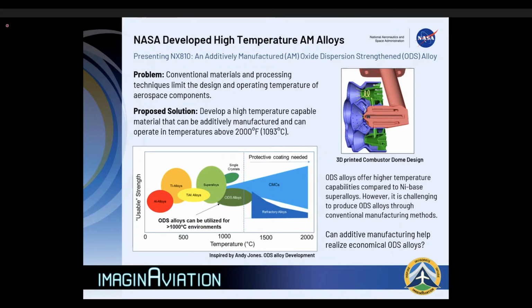But if you look at the graph here on the lower left, one class of alloys called oxide dispersion strengthened alloys actually provide a huge boost in your usable operating temperatures. So oxide dispersion strengthened alloys, or ODS alloys, were actually worked on a lot back in the 70s and 80s. And they showed really fantastic properties. The issue is, for an ODS alloy, what you want to do is incorporate nanoscale oxides into your metal alloy. The problem is doing so is really difficult.